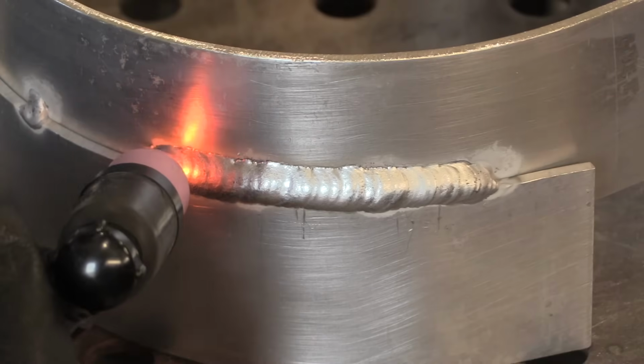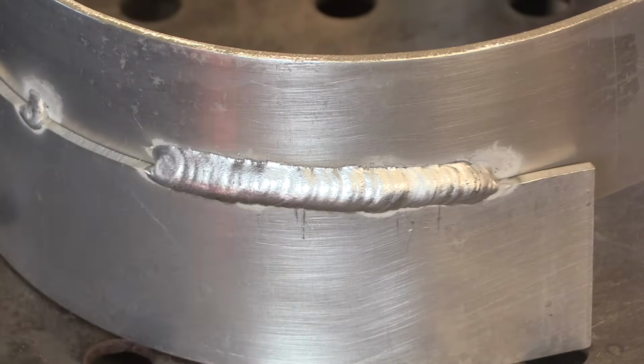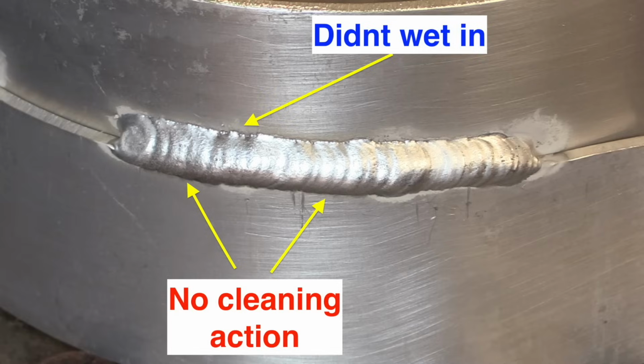So that got me thinking about what effect that would have on a normal lap joint, on how the bead wet out on aluminum. When you don't have enough flow rate, you don't get any cleaning action. And the bead acts like solder that doesn't have any flux, just doesn't wet out like it should. So a normal reaction would be to increase the cleaning action on the AC balance, when really all it needed was a little more argon flow to let that cleaning action go where it needs to go, and let the bead flow out.